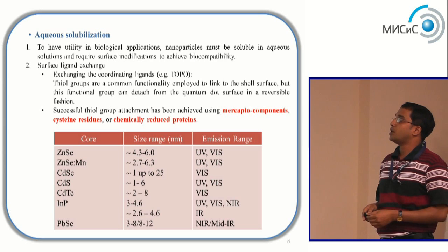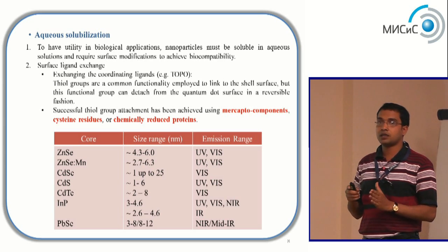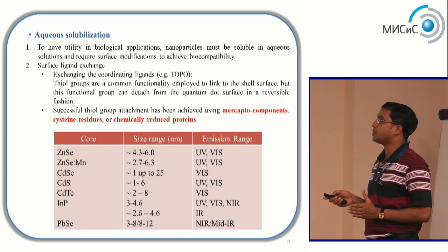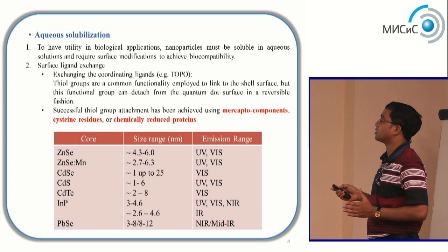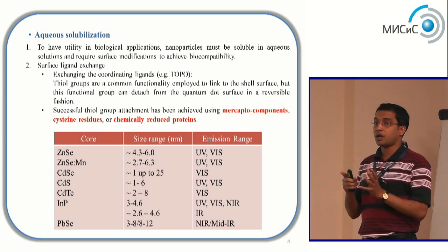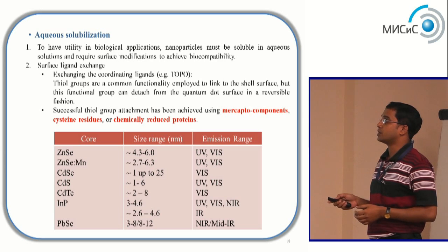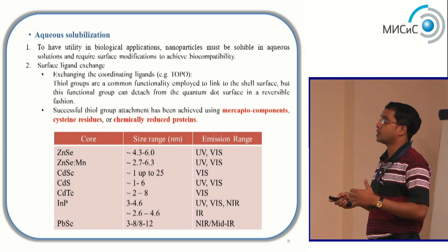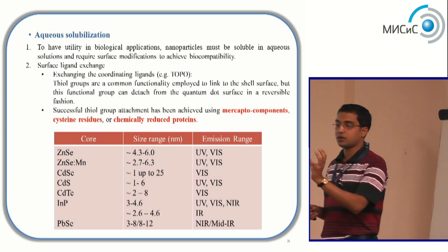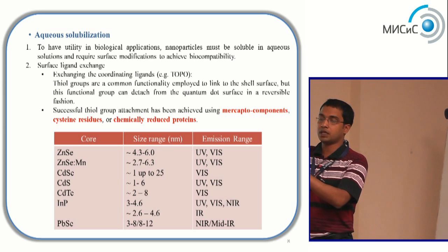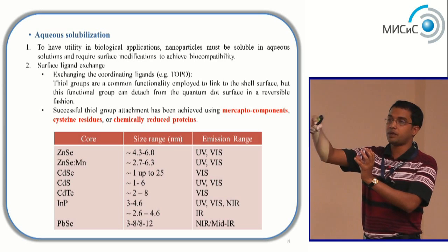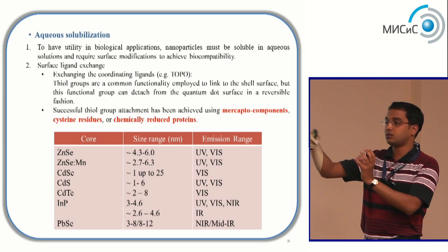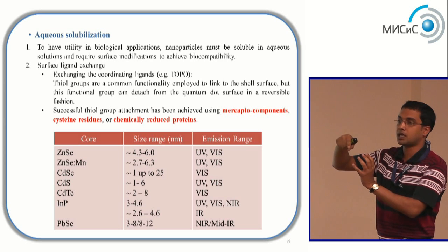After that, for our biological application, the quantum dots have to be water soluble. For biological application, the nanoparticle must be soluble in aqueous solution, because of biocompatibility. And also the surface ligand exchange. I will discuss it, the exchange of the coordinating ligand or TOPO. If you consider a core with a shell, and you want to tag a biological sample, then you need a ligand to tag the biological sample. Otherwise, it will not tag with the core-shell structure.